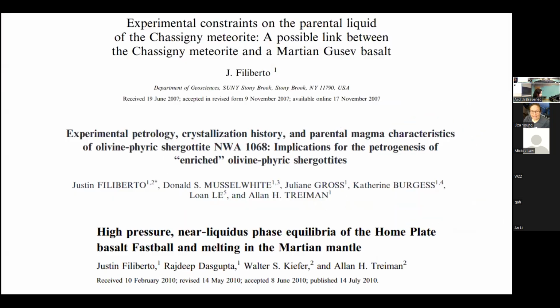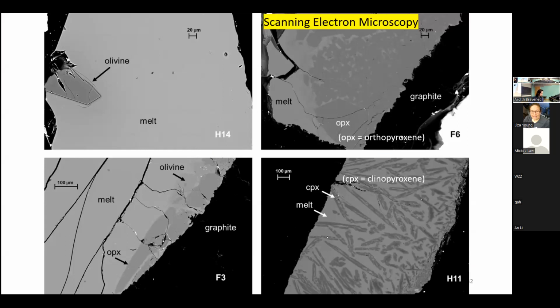Yes, I absolutely agree. So we do try to quench it as fast as possible, which is simply cutting current to the sample while maintaining pressure. And it's hard to say exactly how fast it quenches based on the thermocouple, but it does seem to be as close to instantaneous as we can get in these. So it's not that I'm doing a ramp down, for instance. Yeah, okay, I guess that was my question. Quenching is very difficult.